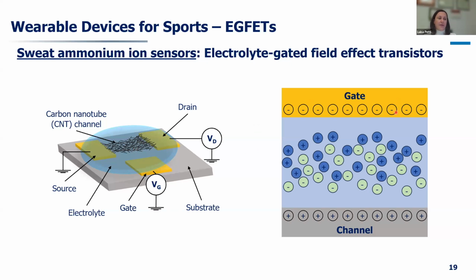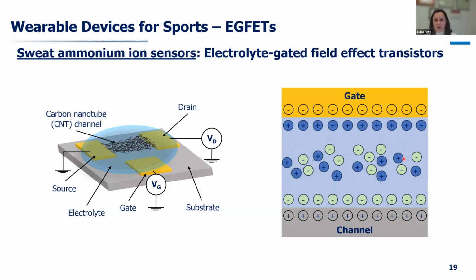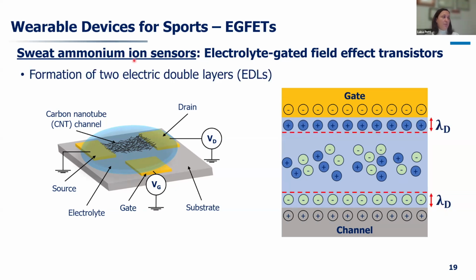So if we apply a negative bias at the gate, what happens is that within the ion-containing solution, so the electrolyte, we have a rearrangement of the ions, so positive ions towards the gate and negative towards the channel, which leads to the formation of a double layer, so 2 electric double layers, so one at the interface of the electrolyte, which in our case we want it to be sweat because that's where we want to do the biological detection of the ammonium ion, and another electric double layer at the interface with the semiconductor.